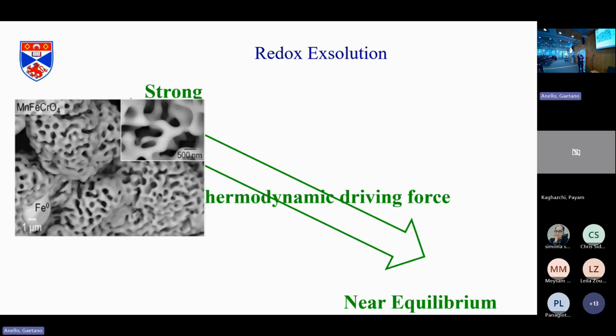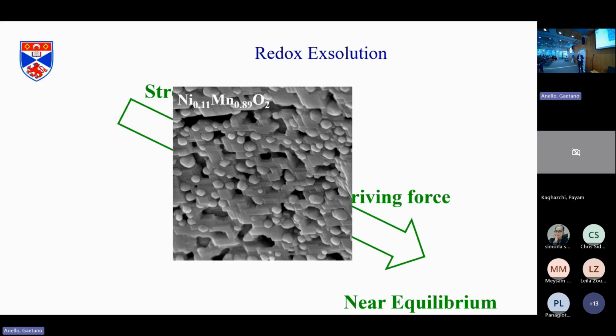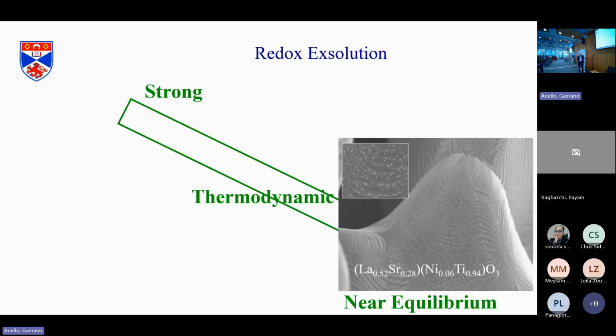So you can see the original grains are still there. And these may be quite good catalyst supports. But that happens with the iron being produced and the iron exuding as a metal. Intermediate, we'll see an example of nickel manganese oxide. You've got larger particles that are sitting on the surface. They're exsolved, but it's really a composite. And it might be a fairly stable composite, but just because you form a composite doesn't mean it's going to be good. And then we call the emergent materials, which I'll say a bit more about.